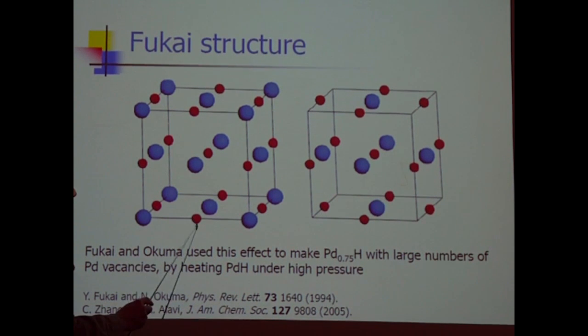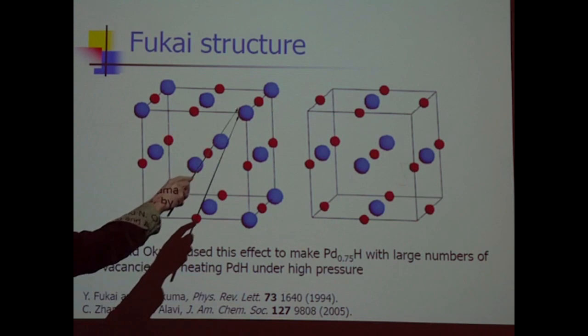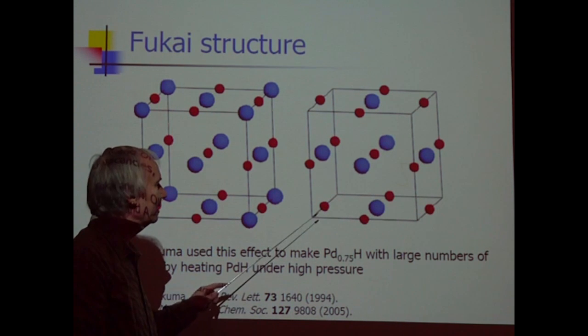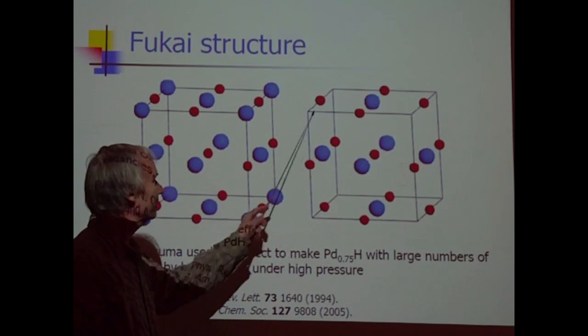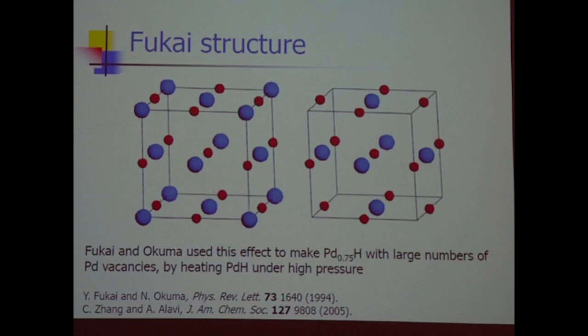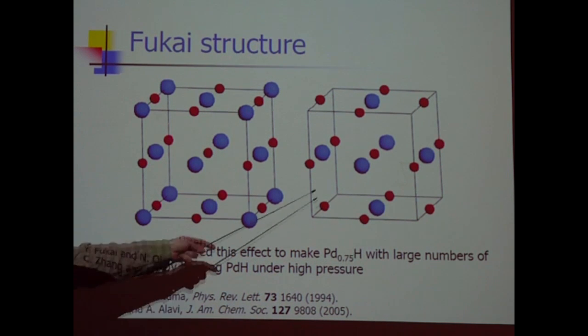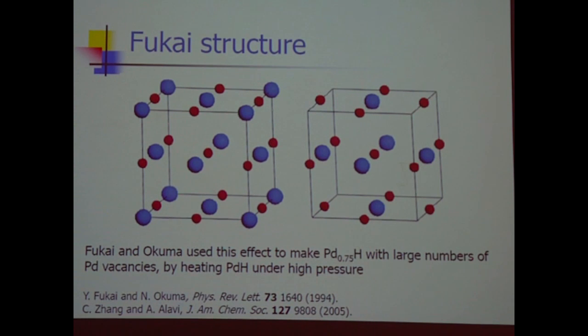If you start with palladium hydride, so again, FCC structure, chessboard on the bottom, shift to chessboard here, another chessboard on top. Well, here's what happened in Fukai's experiment. There's a lot of palladium missing. And what Fukai found is that 1 out of every 4 palladium atoms, by the time he was done with this high temperature, high pressure, high loading processing, had vacancies produced for 1 out of every 4 palladium sites. From my perspective, this is really, really interesting. In a sense, what Fukai makes, I think, is exactly what we want.